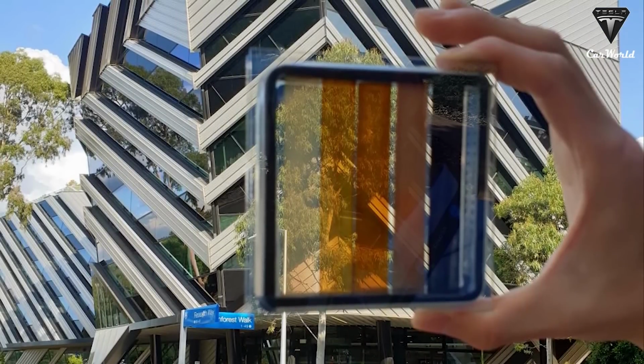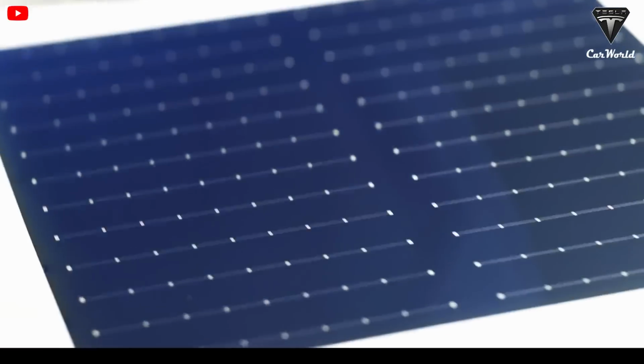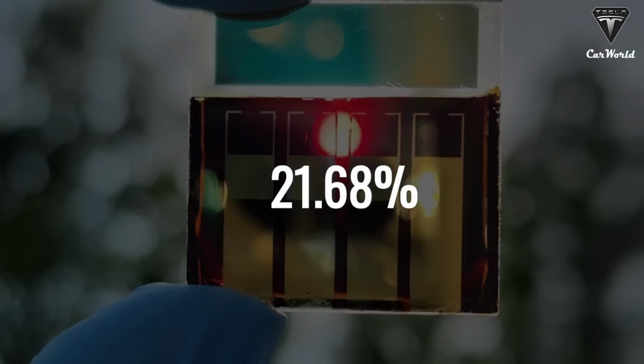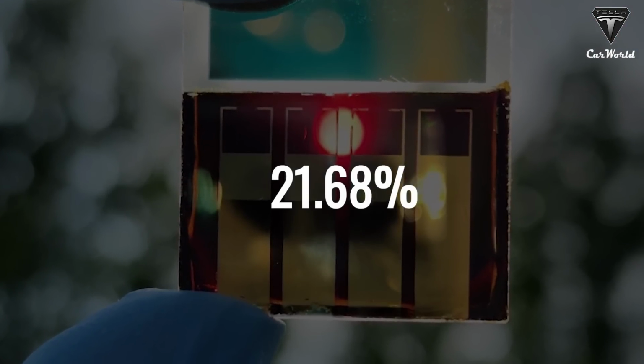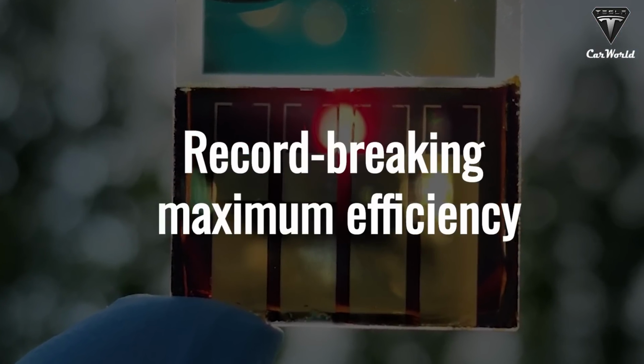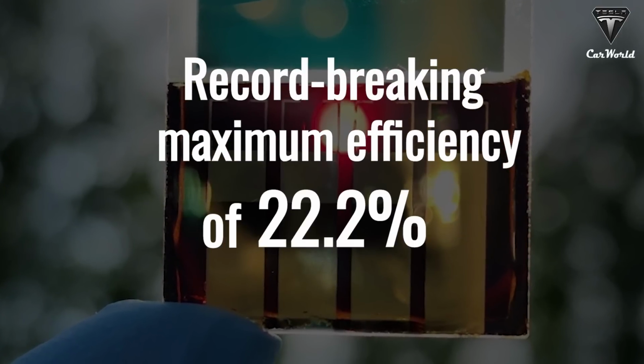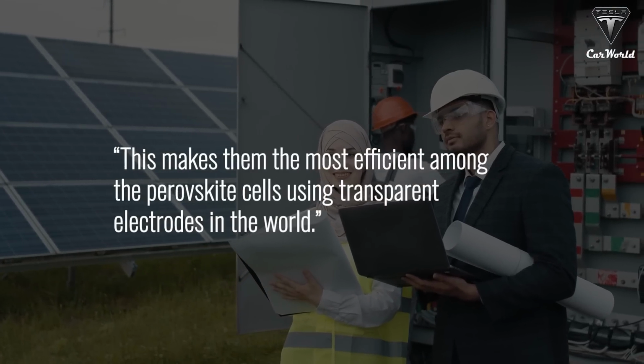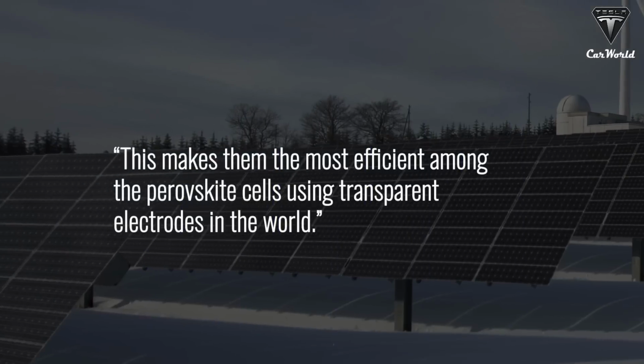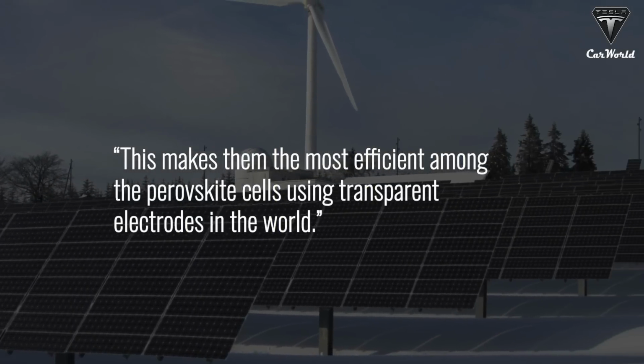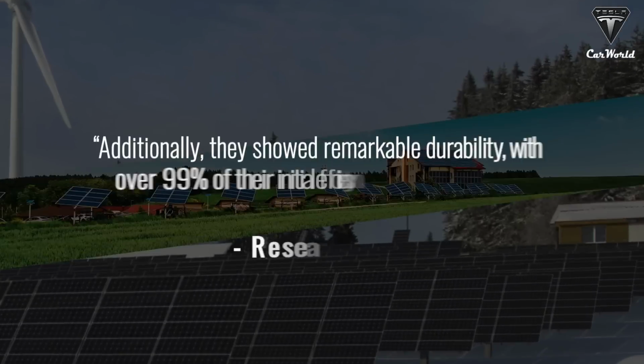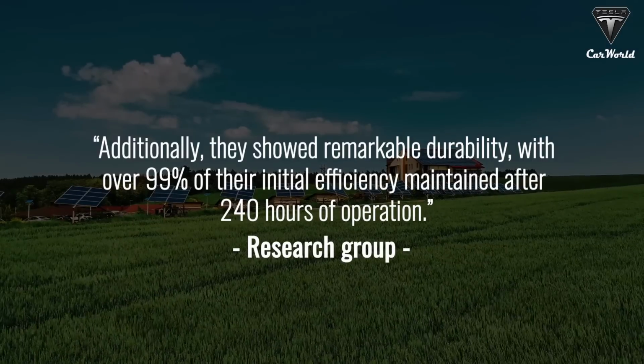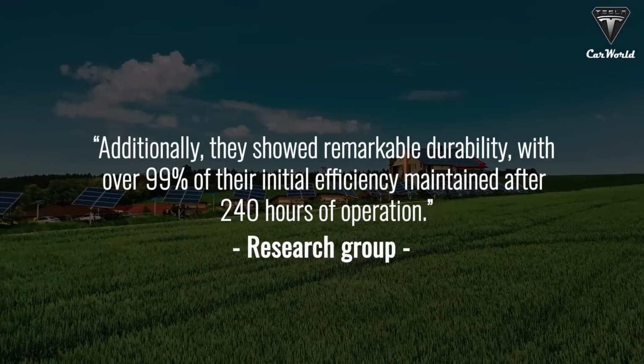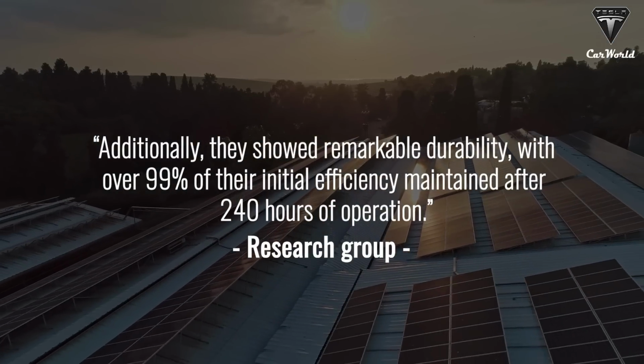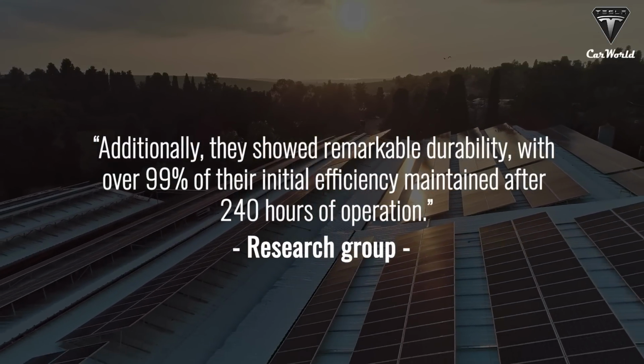The semi-transparent solar cells achieved a certified efficiency of 21.68% and a record-breaking maximum efficiency of 22.2%. This makes them the most efficient among the perovskite solar cells using transparent electrodes in the world, the research group said. Additionally, they showed remarkable durability, with over 99% of their initial efficiency maintained after 240 hours of operation.